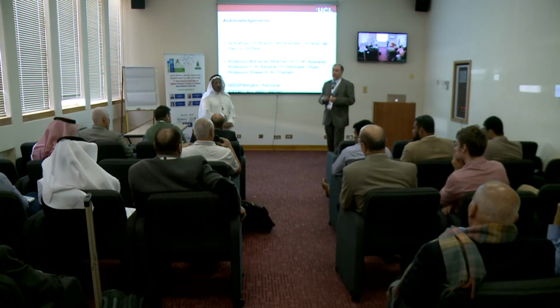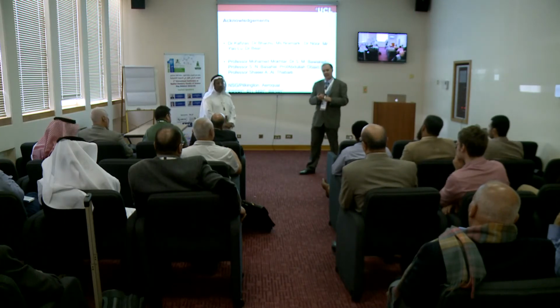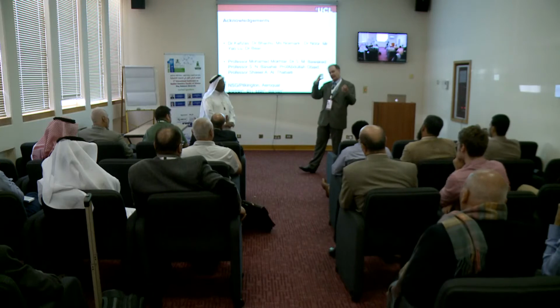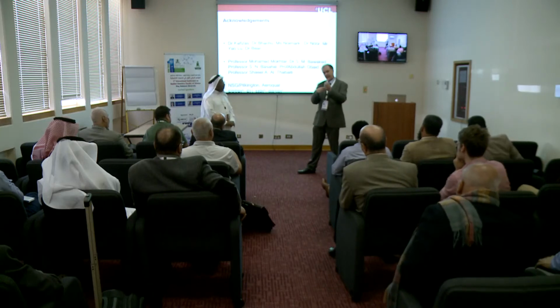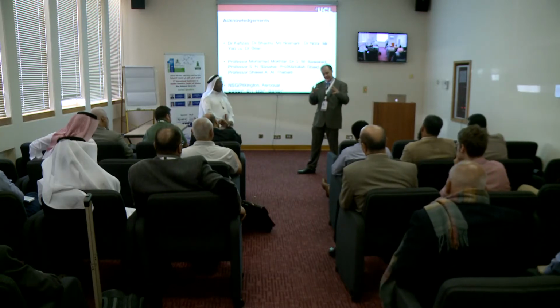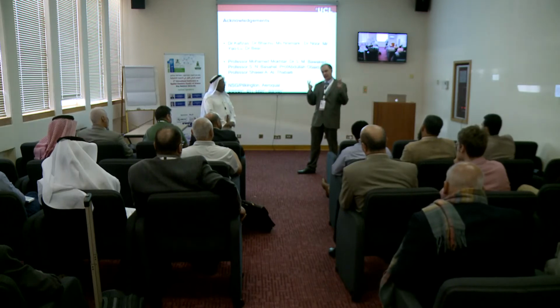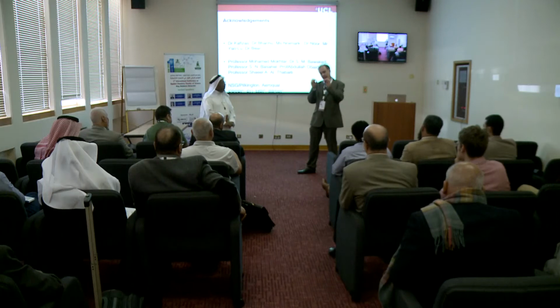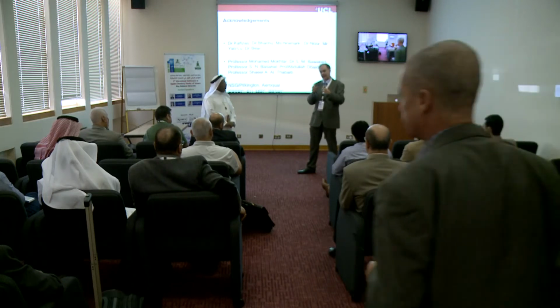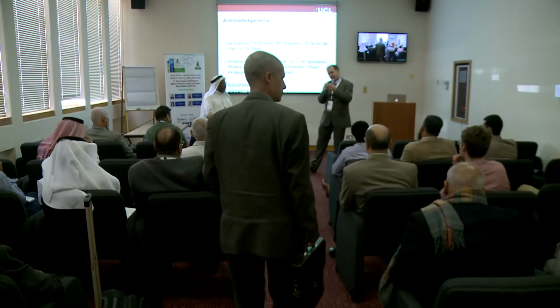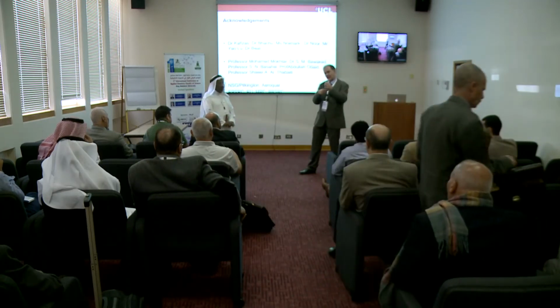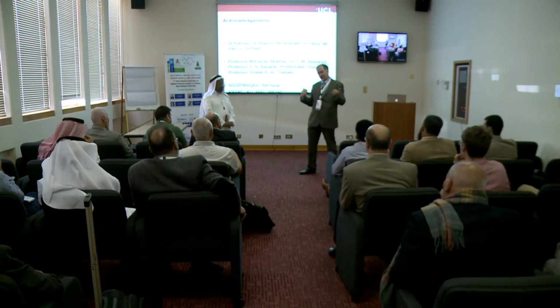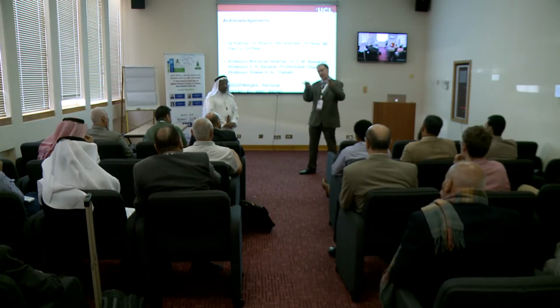Is that the resin? What we typically use is a fluorinated polymer, which we coat the titanium dioxide with. But typically, for the titanium dioxide or the silica, we have to have 2 length scales for the nanoparticles that we use. So we have very small ones and slightly larger ones, some around 10 nanometers, some around 100 nanometers. And by having different length scale nanoparticles with a fluorinated polymer coating, that gives rise to superhydrophobicity. So you need a combination of all those.